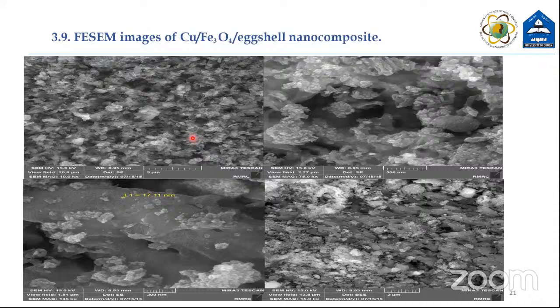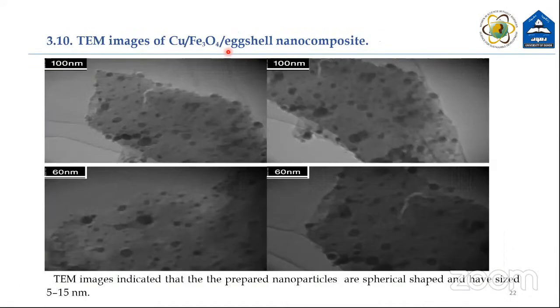Field emission SEM image of the nanocomposite is to determine the shape and morphology of the nanocomposite, and confirmed that copper and magnetite are homogeneously distributed on the surface of eggshell. And this nanocomposite is used as a heterogeneous catalyst because it is composed of two different catalysts, copper and magnetite. TEM image of the nanocomposite indicates that the prepared nanoparticles are spherical in shape and have a size between 5 and 15 nanometers.